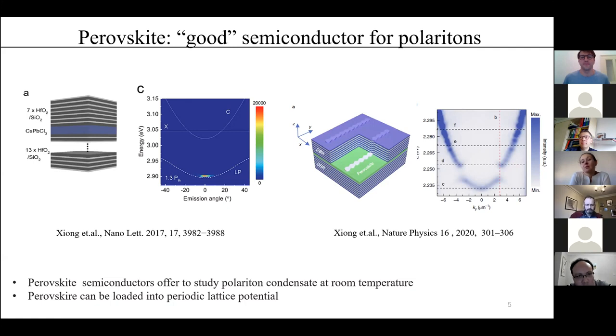In this, we measured this material without a microcavity. Firstly, we found that it looks very easy to lase. I mean, if we do not put in the microcavity, I believe the lasing wavelength depends on the size and the thickness of the perovskite we grow. Usually we see it is around 525 nanometers, or sometimes even around 530 nanometers.